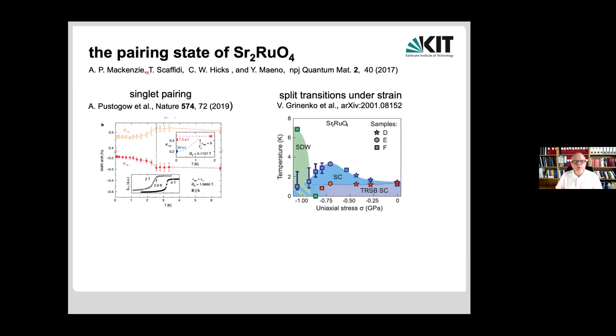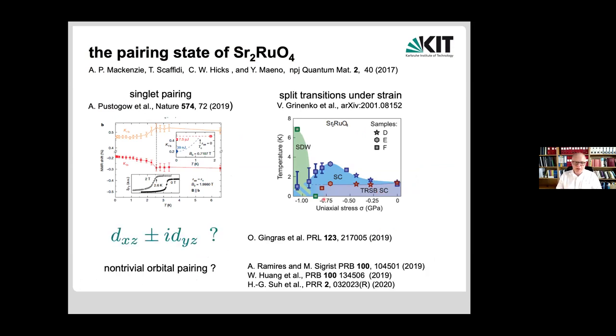Some quite recent review, and there's also a lot that happened since. For example, Stuart Brown and Andrei Pustogow and collaborators found that this seems to be much more likely to be a singlet pairing state than one used to think. And we also know from muon experiments that there is a superconducting transition under strain and a time reversal symmetry breaking transition that is split by applying strain, and something that, if you take them together, might well be a good argument, for example, for a two-dimensional reducible representation, such as an xz plus i yz superconductor.